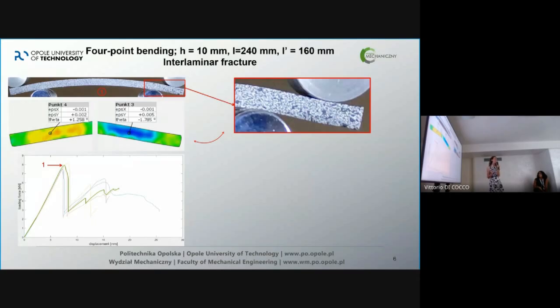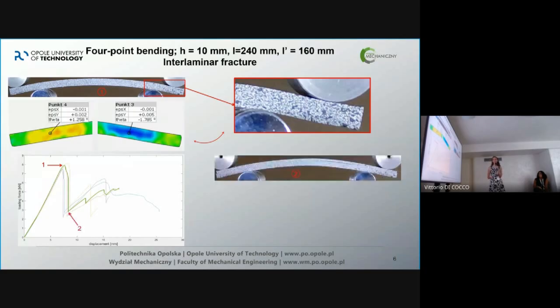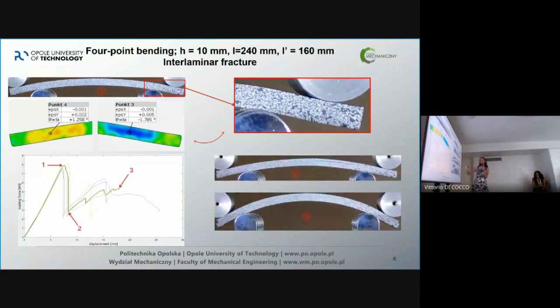But what happened in my situation just after this beautiful specimen? You can see that there is no visible crack, you can't see anything. Just on the colorful pictures, you can see that the angle is almost 2 degrees. So you can see that it's going to crack. And of course it cracked. And like milliseconds later, here you can see a crack.